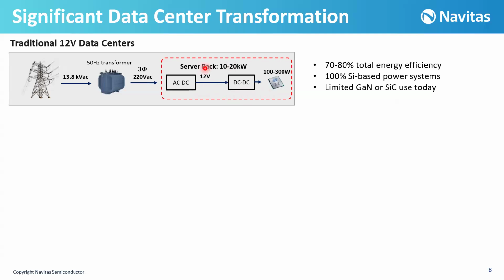The power density of this server rack is 10 to 20 kilowatt, and the components use 100 to 300 watts. The total energy efficiency of this architecture is only 70 to 80%, and the reason is that this architecture is based on only silicon power devices. Even with the limited gallium nitride or silicon carbide usage that we have today, we have a low efficiency.